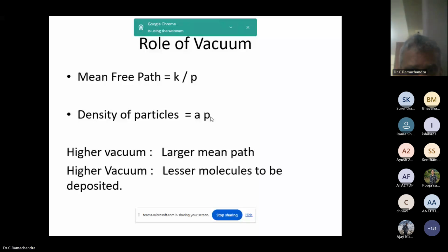But if I reduce the pressure, the number of particles also will reduce. In the process of improving the mean free path, I am losing the particle density. That means fewer particles, so the deposition rate will be less and it will take much more time. That is not compatible with industry. We cannot wait one day for deposition. It is not at all acceptable. It should be in a few minutes or so. Therefore, there is an optimization or compromise between the deposition rate and the mean free path so that films will be deposited. This depends on the chamber design and we need to work it out.